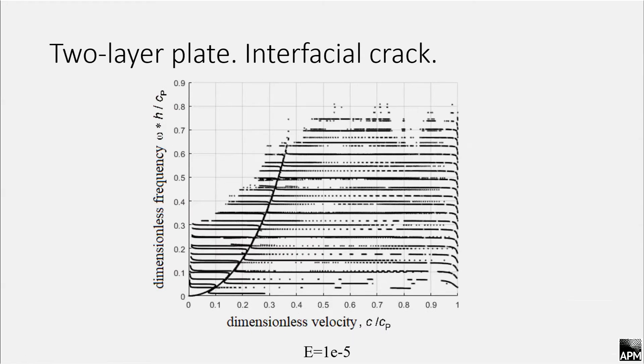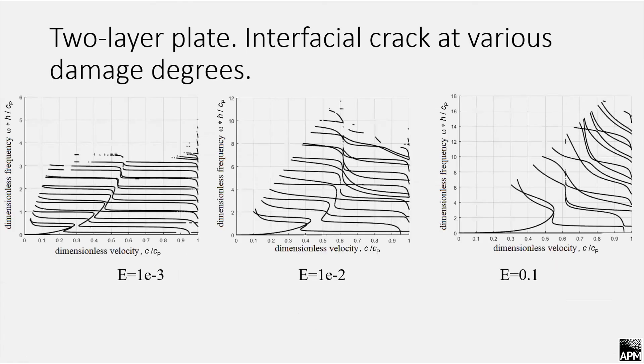Here, we can see that deformation modulus for middle layer equals 10^-5. At different values of Young's modulus for the middle layer, we can see a different picture of dispersion curves. From looking at this graph, we can see that it is possible not only to find the damaged element, but also to estimate its condition.